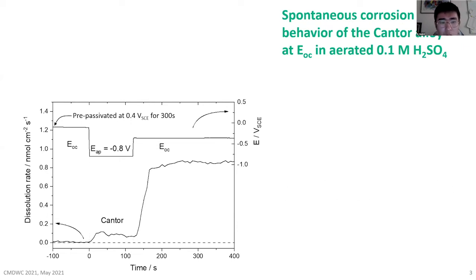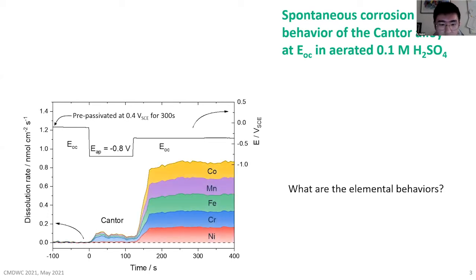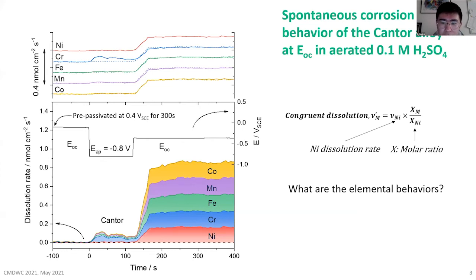So during this process, what are the elemental behaviors? With the help of AESEC, we can distinguish the individual contribution of each element, and they are shown in the figure. With some simple calculation, we can calculate the congruent dissolution based on the dissolution of nickel, because the XPS results demonstrated that nickel contributes little to the formation of the passive film. After this calculation, we can compare the real dissolution with the congruent dissolution. We can see that in the cathodic activation step, the real dissolution rate was much higher than the congruent dissolution rate. It implies that this is passive film dissolution at this step.